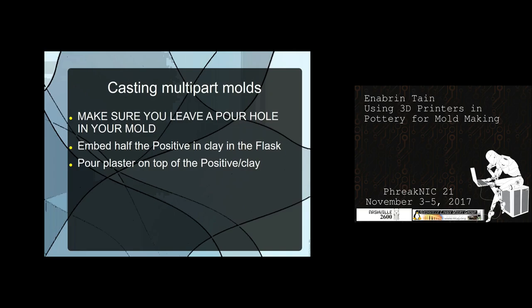What I use is saddle soap — you just spritz saddle soap on it and that'll keep it from bonding. I've also used baby shampoo, and that works just fine. For some complex shapes, you have to have vent holes so air can escape. For really complicated shapes you do have to do some extraordinary things.